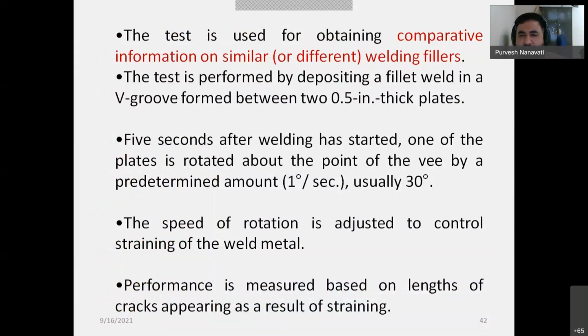After 5 seconds it bends, at 1 degree per second, and rotation is 30 degrees, and strain is developed, and the length of crack that appears after straining is measured. So this test is used for obtaining comparative information on similar or dissimilar welding fillers. It means if you are joining two different materials, carbon steel and stainless steel, and you go for 308, 309, or 310, then you can go for this test.